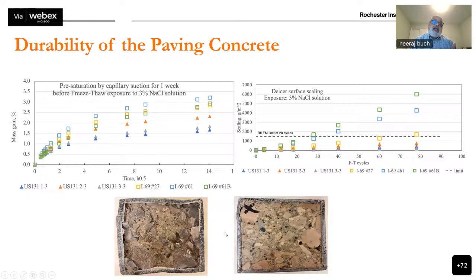So this is a cause of concern, and this will have to be monitored over time. Please remember, these pavements are only 4 or 5 years old, so it's going to take some time for the scaling to completely manifest and show if there truly is a problem. What I'm showing you here are lab tests under fairly aggressive conditions. This is not what the real pavement is exhibiting; this is what the lab specimen is exhibiting. A real pavement takes time, whereas in the lab it's very aggressive testing to exaggerate the effect of sodium chloride. But there are some indications that the I-69 concrete may be freeze-thaw or scaling susceptible. That's all I can say, susceptible, because there is no evidence that scaling has taken place. Nonetheless, this is another way to look at the durability of the concrete.